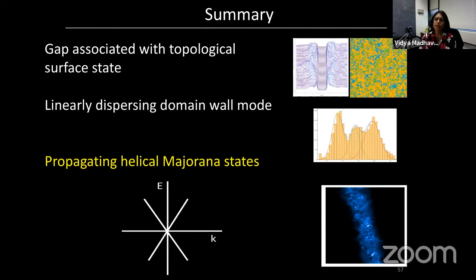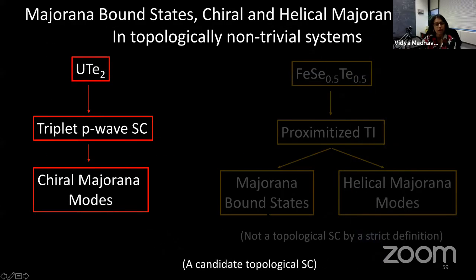Okay, so in this system, it's interesting. I'm not saying that this is smoking gun evidence. There are many questions one could ask, but certainly very intriguing, both the vortex core zero bias bound states, as well as the existence of these propagating states along these domain walls, suggests that we actually have Majorana states in the system. And in fact, these domain wall states are helical Majorana modes that were predicted to exist by Fu and Kane. So I can pause here and take questions before I talk about uranium ditelluride if you wish, or I could just skip uranium ditelluride entirely.